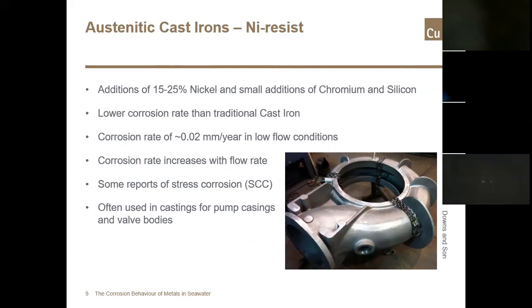And the alloys are often utilised more for larger workhorse jobs. They utilise the strengths. They're typically used for pumps and pump casings, and they can be used in copper and ferrous seawater systems reasonably satisfactorily. However, they can be susceptible to stress corrosion cracking as well. So whilst there are some improvements, there are other issues that again need to be taken into account during the material selection and design process.